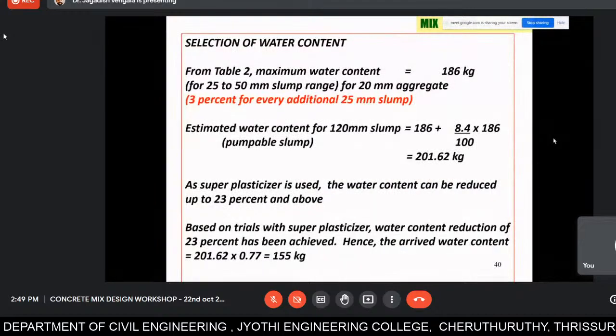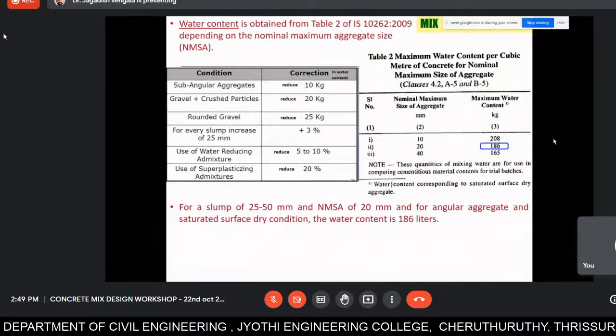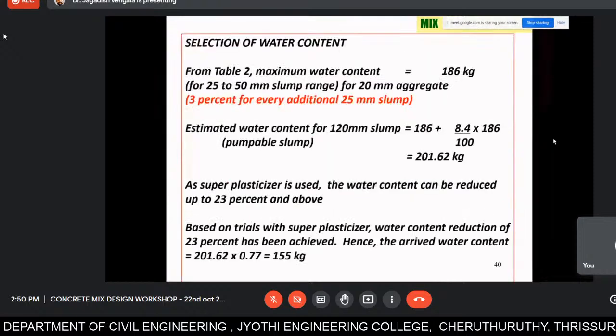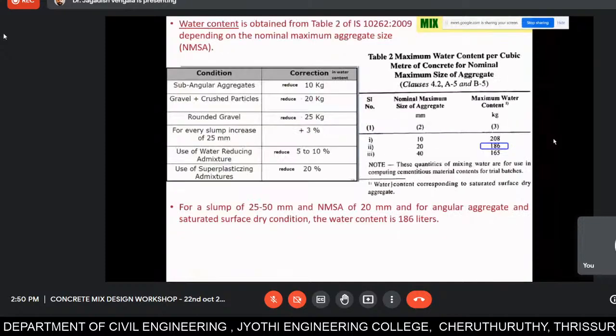So let us go back to our case. So next is selection of water content. So selection is based on Table 2 of IS 10262. There are 3 types of aggregates we use for normal concreting: 20 mm, 10 mm, and 40 mm. 40 generally we go for road works or some other special ones. Typically we go for 20 mm down aggregates. For 20 mm down aggregates, the maximum water content we have to take is 186 liters. So this 186 liters is for the slump of between 25 to 50 mm. Please remember, this particular table is for 25 to 50 mm slump. 20 mm down aggregates, 186 liters, and that too in saturated surface dry (SSD) condition, right?